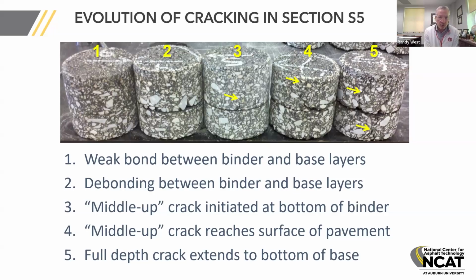Core number four shows where a crack has then worked its way up from that debonded interface all the way to the surface. And then core number five is where the pavement is really damaged because of that weakness, that bond issue. The cracks are working their way from the interface to the top, and that lower layer is also cracked now in that particular core. So this is the phenomenon that we see with a debonded or poorly bonded pavement construction, and it will lead to premature cracking, premature rutting, or even continuous progression of cracking throughout the pavement structure.